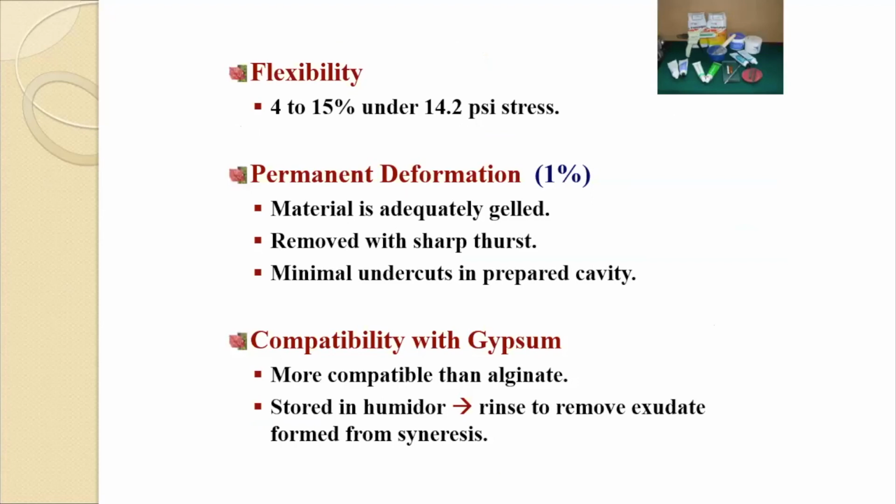Coming to your flexibility, it is 4 to 15% under 14.2 psi stress. You need to learn all these values a little. The rest you can basically understand: what each material is made up of and how it is different from the other, how you need to make the impression. That is most important, what I feel. Then compatibility with gypsum, it is known to be more compatible than your alginate.